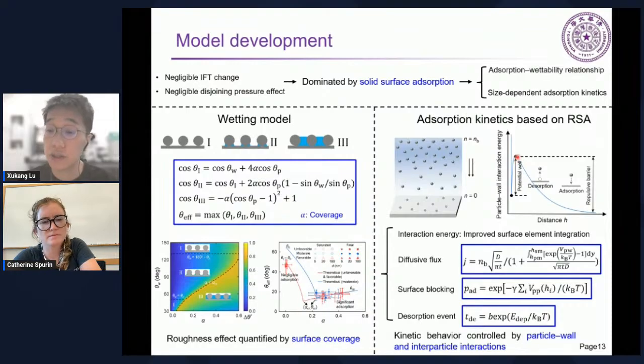And usually a larger particle will have a higher repulsive barrier, and so the efficiency will be reduced at a larger particle size. And after this repulsive barrier, the particle will fall into this potential well, and that means it is actually adsorbed. But that doesn't mean it's permanently fixed. You can imagine that when the well is shallower, maybe the particle will escape from the surface and lead to instability. And that usually happens at a smaller particle size.